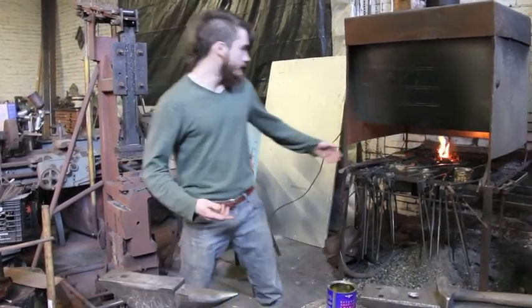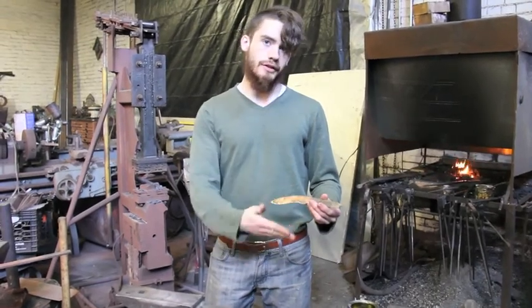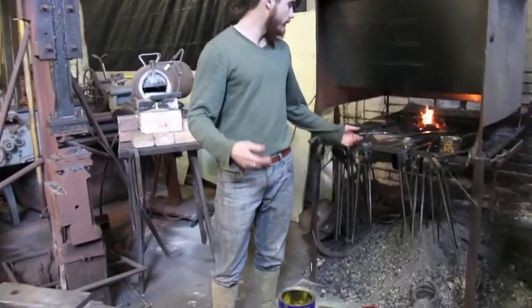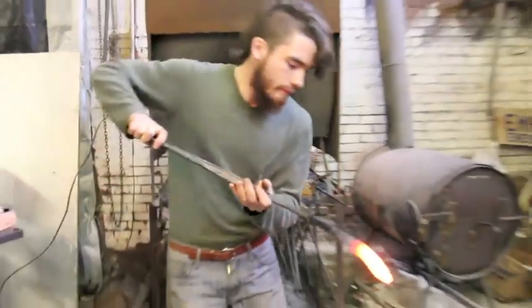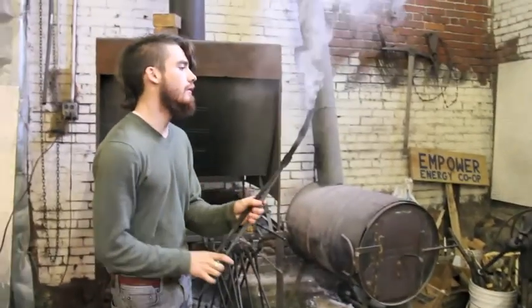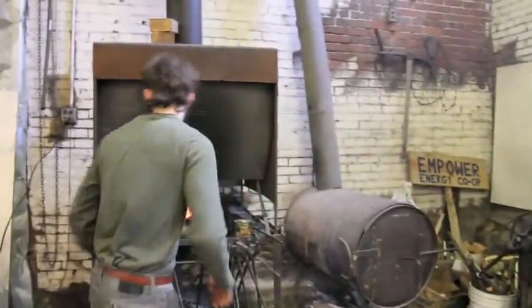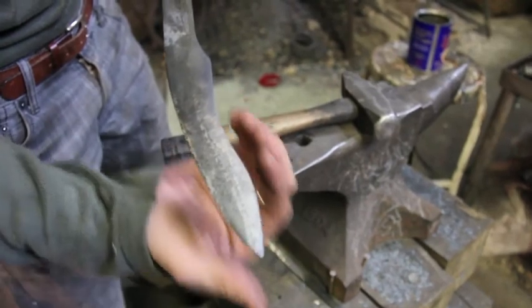What I'm doing right now is working on the heat treatment of some of these blades. These are actually pattern welded, so there are four bars of steel going horizontally down this blade. What I'm going to do now is just heat it up and quench it in oil, so it will be hardening the blade. You can see all the different steels right there — the darks and the lights. That's the high carbon and that's the medium carbon, and on the edge is the more high carbon.